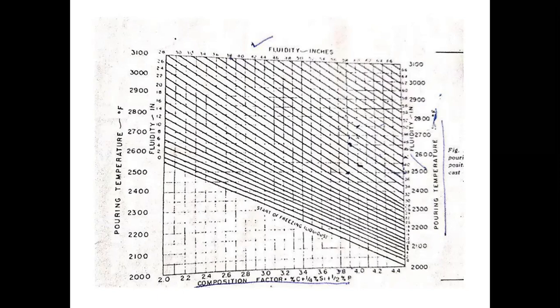A non-pressurized system will be able to fill the mold fast. Because in SG iron we are using the filters, so that slag will not go. In case of ductile cast iron, what happens is, if we increase the thickness of a casting, or increase the choke area, non-pressurized, then metal will go fast, but the pouring head will not be maintained. As per the operator condition, some pouring operators pour fast, some feed it slowly. At that time, the pouring head will not be maintained. Then we will have a cold shut defect.